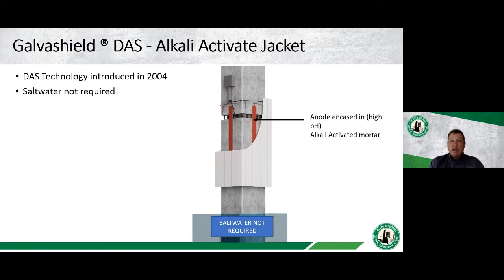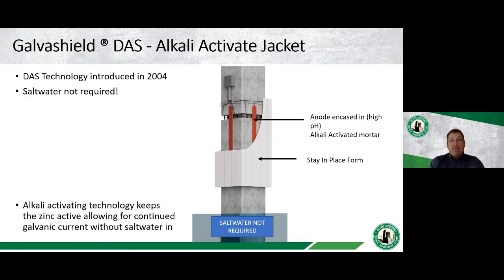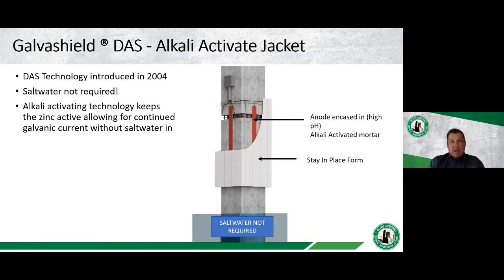And the one thing to note with it again is that because it can be used in the higher elevations, salt water is not required. What it relies on is basically a zinc anode that's encased in a high pH material. This activates the zinc, allowing it to provide a corrosion current. So we don't need salt water. Salt water does not need to wick up and down inside of the jacket.